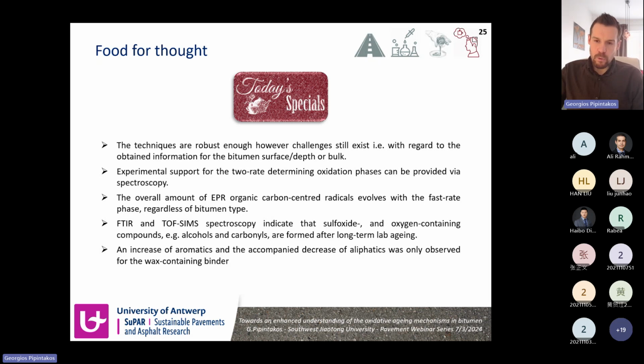Besides this, we were able to support indeed two rate-determining oxidation phases, as mentioned some years ago in the literature, and also to prove that radicals are formed and evolved during the fast rate phase, regardless of the bitumen type, because we had different types of bitumen and distillation process. And we also proved that some chemical products can be formed, like sulfoxide and oxygen-containing compounds, especially after long-term aging. And also that there was an increase of aromatics and decrease of aliphatics only for the wax-containing binder.